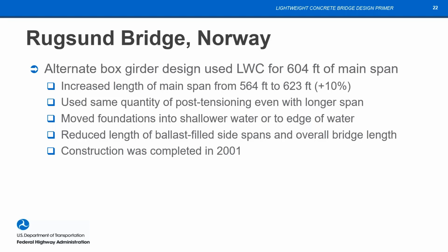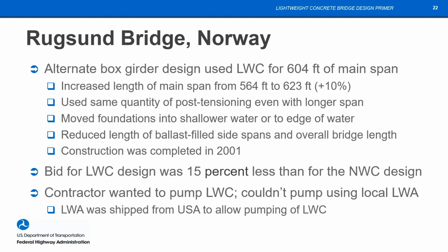The main span was increased by 10%. And this is a project that, unfortunately, I don't have a photo of here, but it's over a fjord. So by increasing the main span by 10%, you're moving the foundations up out of the deep water. So that was very significant. The bid for the lightweight design came in actually 15% less than for the normal weight design.